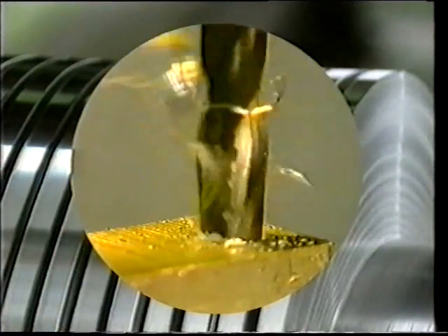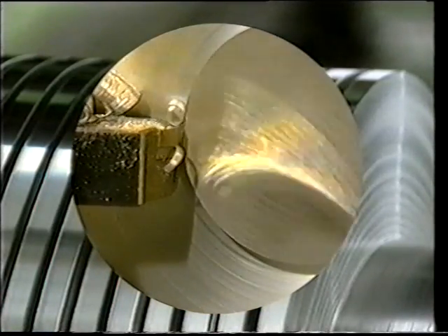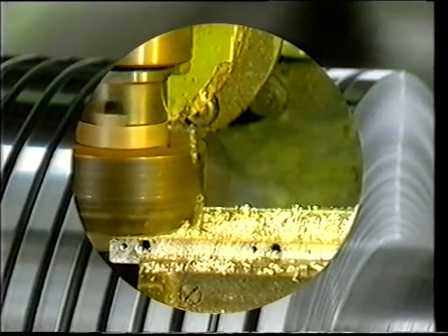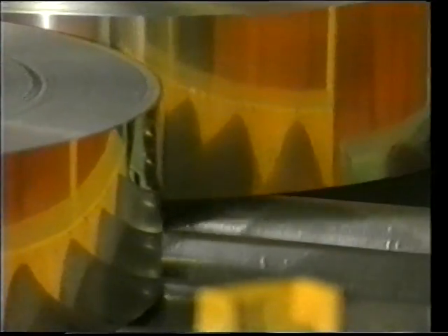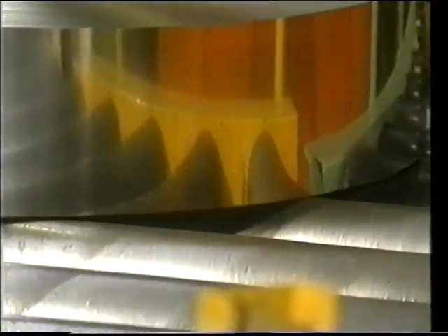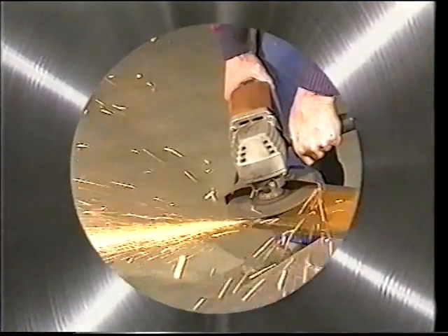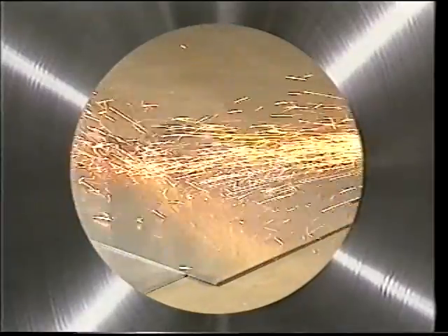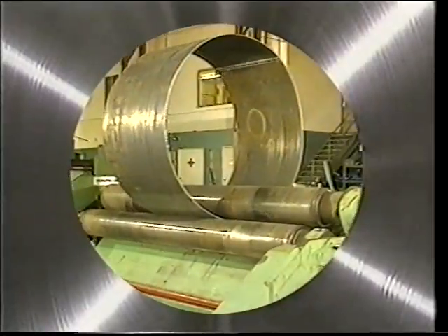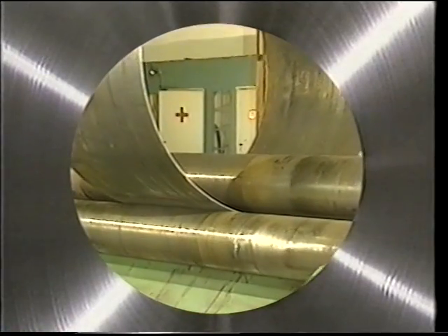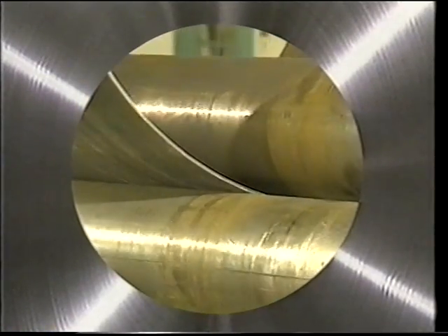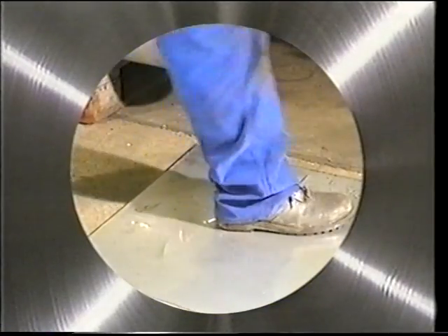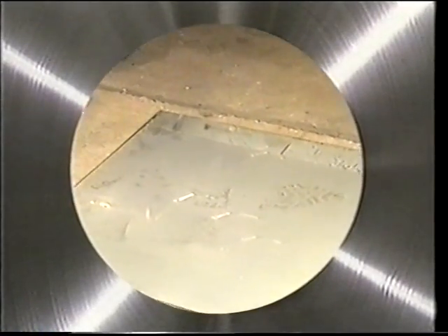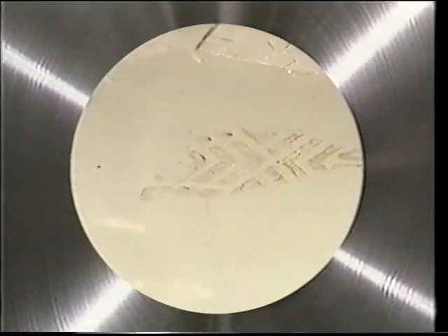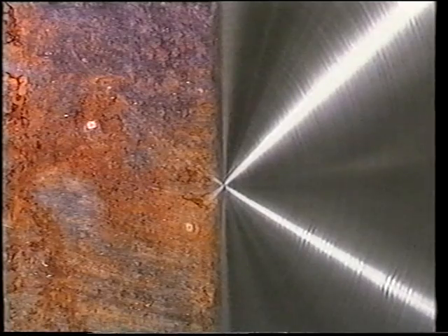Mechanical operations such as drilling, turning, or milling destroy this layer. Normally it regenerates immediately, provided the surface remains completely free of contaminating substances. These include splashes of foreign metals or deposits of carbon steel produced when white and black materials are processed on the same machine, or contamination caused by footprints, perspiration and dust. The resulting damage to the passive layer leads to progressive corrosion, which can very quickly destroy the usefulness of valuable equipment and facilities.